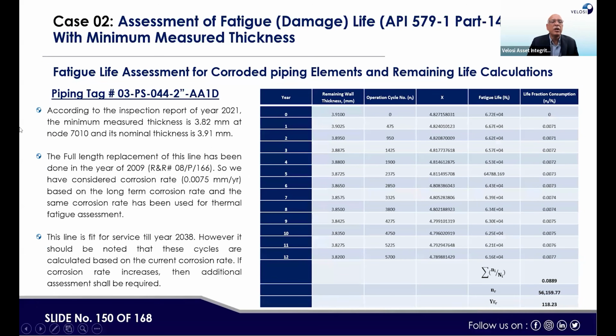So here, if you see the fatigue life assessment for corroded piping element and remaining life calculation for piping tag number this, according to the inspection report of year 2021, the minimum measured thickness is 3.82 mm at node number this and nominal thickness is this. The full length replacement of this was done in that period. Now, the line is fit for service till year 2038. However, it should be noted that these cycles are calculated based on the current corrosion rate. If the corrosion rate increases, then additional assessment would be required.